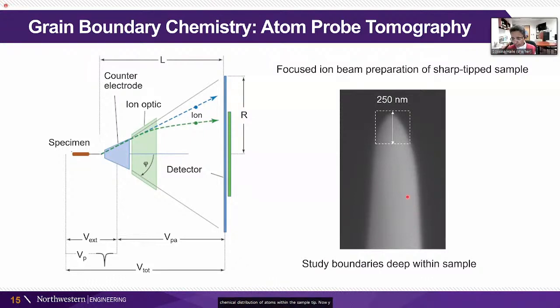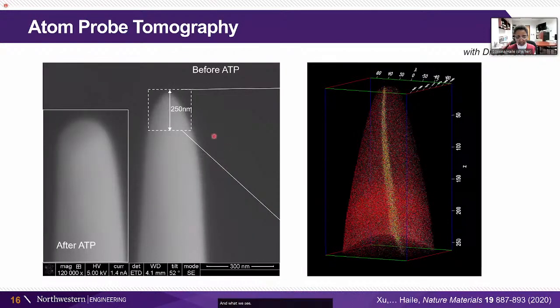Now, you have to be very good. Again, my student was very good at this, to be able to cut this pin and be able to actually have a grain boundary within this sharp needle region. And what we see, here's an example of one. Here's before running the atom probe tomography, and here now we've lost that top sample of material. So we're probing this amount here.